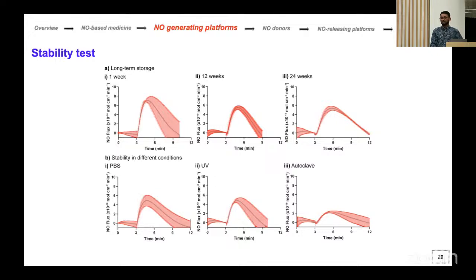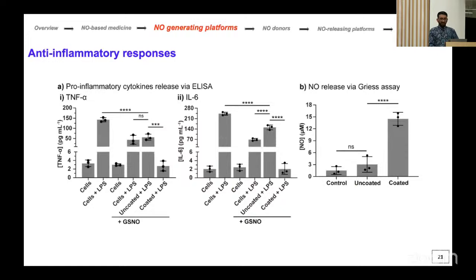basically NO generation under different conditions. For example, if we autoclave them and measure NO after 24 weeks, and if we put them under light and measure NO generation ability after 24 weeks. And then we look at the anti-inflammatory effects.